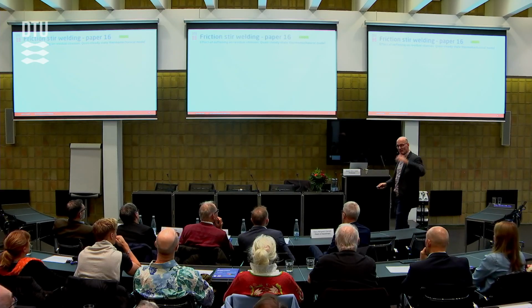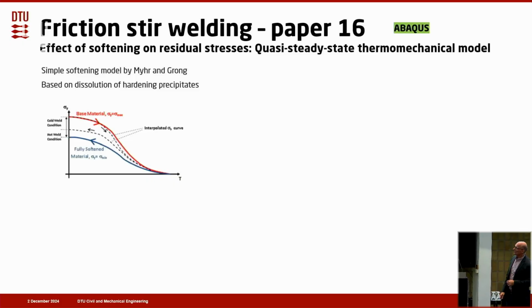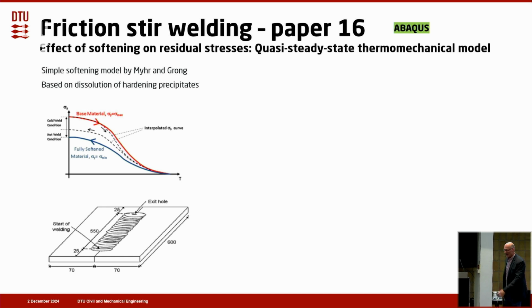So in friction stir welding, we also looked at the effect of softening on residual stresses. This was the quasi-steady state mechanical model I showed before in Abaqus. And we used a simple softening model by Myhr and Grong. It's based on dissolution of hardening precipitates. So the red curve is when it heats up. The blue one is when it cools down. And here we have this example.